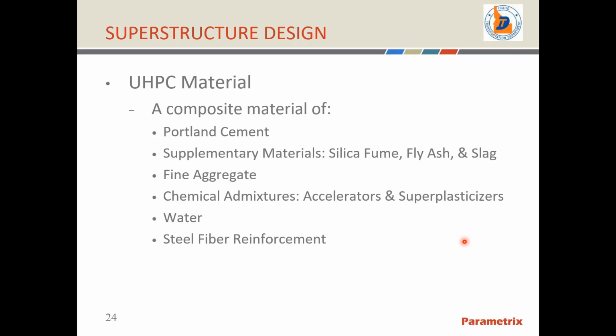So ultra high performance concrete is really a composite material. It includes Portland cement and supplementary materials like silica fume, fly ash, or slag. Uses fine aggregate, not coarse aggregate. Has chemical admixtures like accelerators and superplasticizers. Of course, uses water. And then another key ingredient is the steel fiber reinforcement that goes in this material. The steel fiber reinforcement is typically about 2% by volume, and it consists of little half-inch long steel fibers that are about 8/1000ths of an inch in diameter.